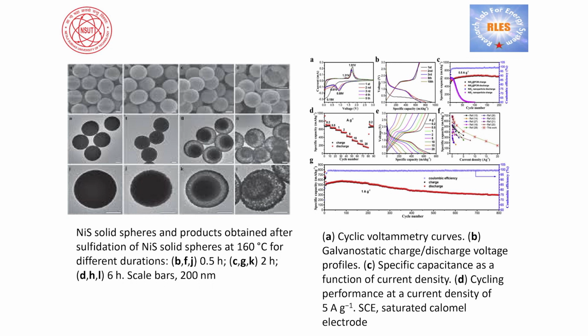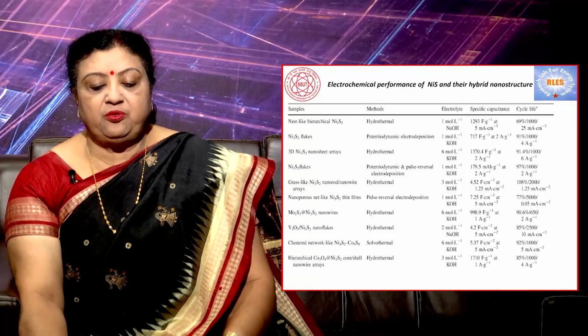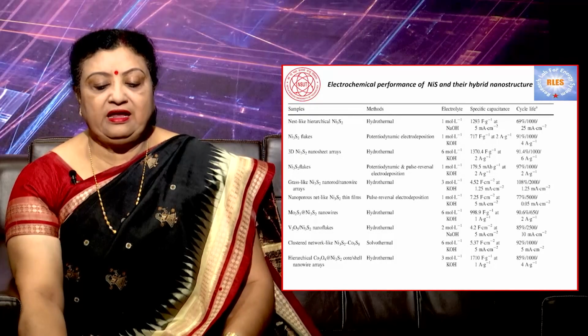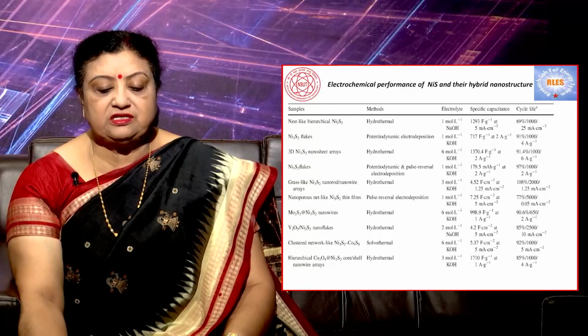Here are the cyclic voltammetry curves, the galvanostatic charge-discharge voltage profile, specific capacitance as a function of the current density, cycling performance at a current density of 5 ampere per gram, and the saturated calomel electrodes. So, electrochemical performance of NiS and their hybrid nanostructures.